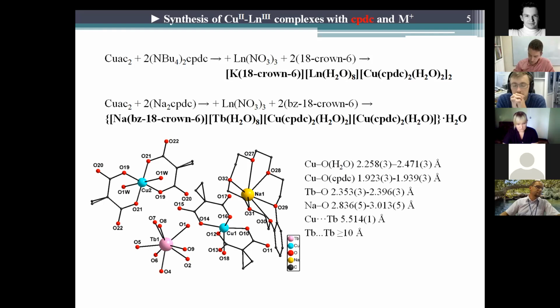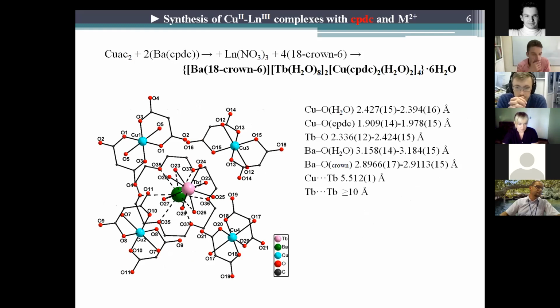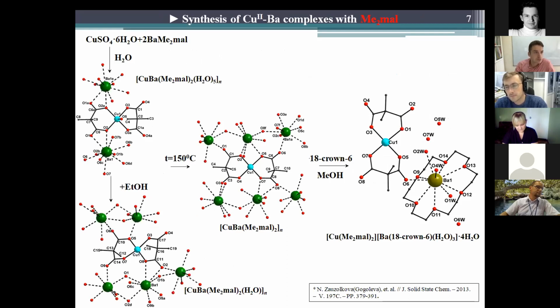an octahedral environment. When we used a barium salt of cyclopropane dicarboxylic acid, we were able to synthesize new trimetallic complexes, with a combination of copper, barium, and lanthanide in it. All copper atoms are situated in an octahedral environment with 2 water molecules, and the barium atom coordinates oxygen atoms of the crown ether molecule. The lanthanide atom coordinates 8 water molecules and shares 4 of them with barium. Previously, we have shown that copper can form a range of heterometallic complexes with barium and dimethylmalonic acid. Crown ether on the barium atom made complexes much more soluble in organic solvents.